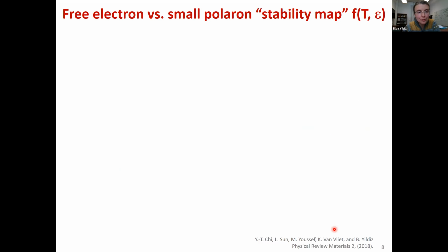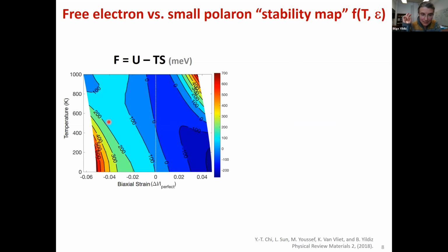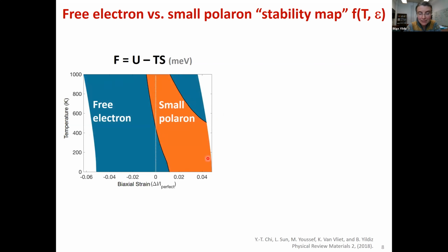All right, so what do we find in terms of the relative stability of free electrons versus small polarons as a function of temperature and strain? So here we can look at the self-trapping energy that I have defined on the previous slide, and the units are in milli-electron volt. And we can see the border between negative and positive energies as a function of temperature and as a function of strain, compressive and tensile strain. And those borders will be the borders between the dominance of the free electron and the dominance of the trapped small polaron. And so this gives us a phase diagram for the stability of these two different types of electronic defects.